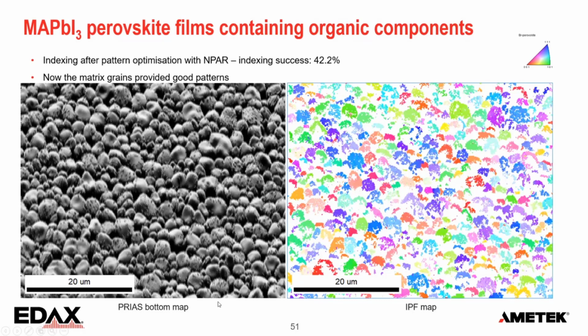That's a picture that's also constructed from the EBSD patterns. Here, for every pattern, every pixel, we are looking at a band of points at the bottom of the diffraction pattern, looking at the intensity there and building a picture on that. And PRIAS bottom is extremely sensitive to topography. So that gives you a beautiful topographic sample where we can recognize the small grains sticking out. You have the shape of all those grains. And in most cases, we get usable EBSD data, just over 40% indexing, but enough information.